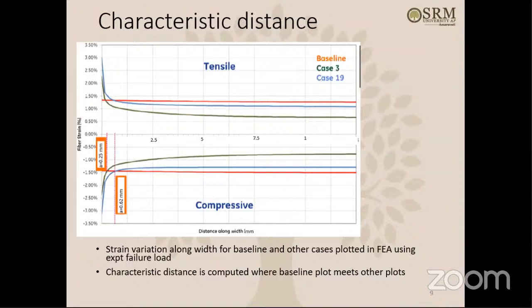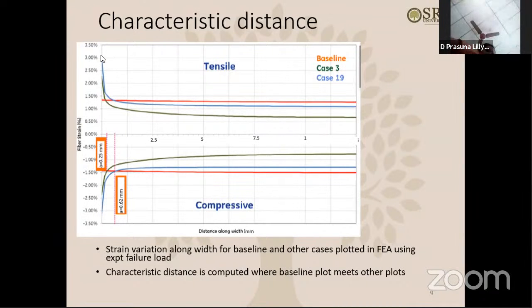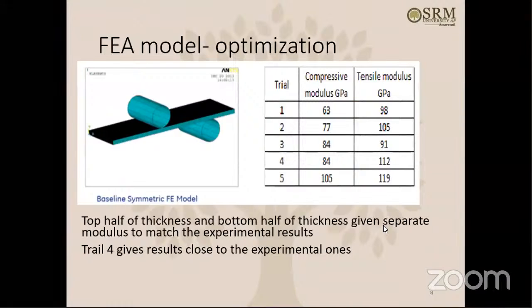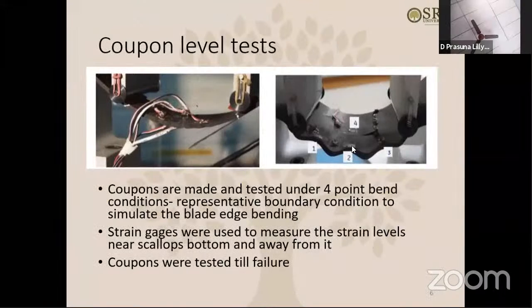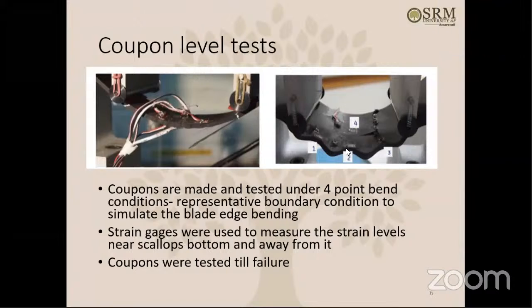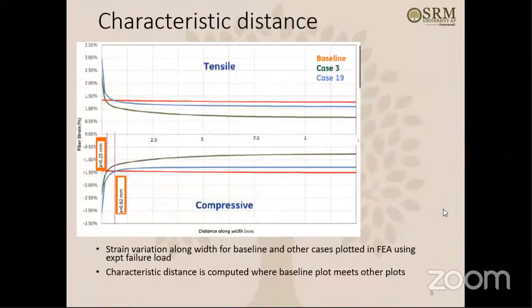So as you can see, the tensile strain variation along the width and the compressive strain variation along the width. And if you look at the baseline plot, where the baseline plot is meeting this other plot, the strains are very high near the scallop, and as you go away from the scallop, what I'm trying to say here is, if you plot the strain variation along this width, at the bottommost point of the scallop, of course, it will be very high strain, and then as you go along the width, the strain level reduces. That's what happens. Similar thing is happening here. As you can see, the strains are very high.